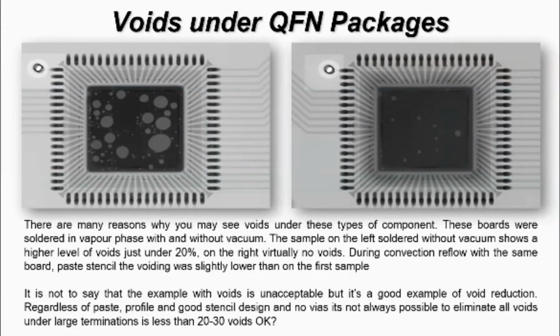Now, voids, there's obviously lots and lots of discussion, just like with via holes in QFN LGA packages. And if voids are not an issue to you, then why work to a tighter specification? If perhaps a product can operate and not have any impact with 30% or 40% voiding, then why are we worried about it? But if you do need it, what is the way of reducing it? Well, another one of the ways is using vacuum. And this is just an example of me running on a production line, same pace, same print, same package, but all we did was turn the vacuum on in this particular example. And you can achieve this with convection and vapor phase, but this example was with vapor phase.